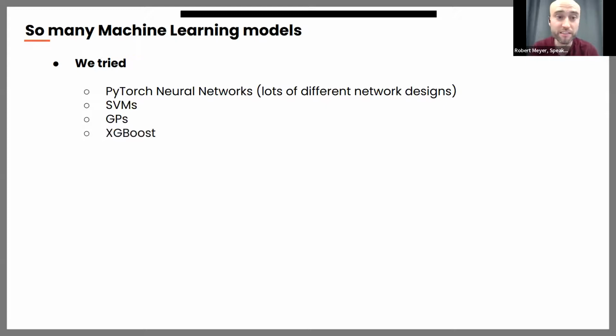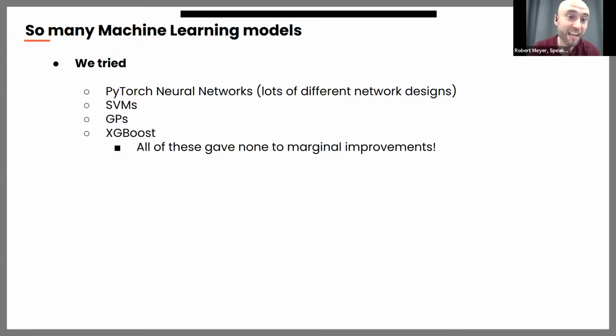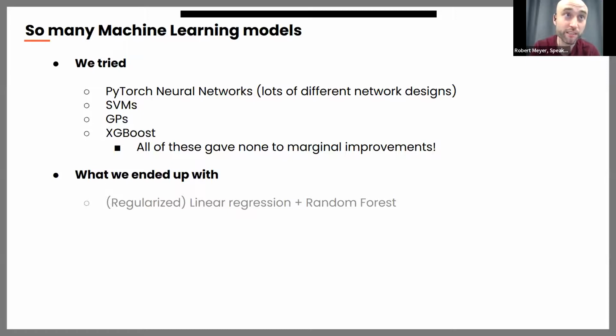But unfortunately, and this can be a reality for you as a machine learning company, the model that you're using doesn't make a huge difference. All of these show none to marginal improvements, and even worse, all of them are very black boxy. What we actually ended up with, which is deployed in production, is a combination of just regularized linear regression, and on top of that, a random forest that corrects the error of the linear regression.